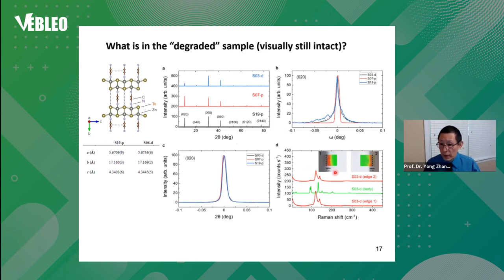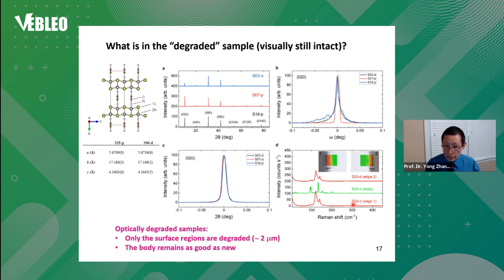To find out what is going on in the heavily degraded sample, we took a piece, cleaved it, and exposed the body of the sample. Then we did a Raman measurement from the edge. We found that in the body part — the green region — the spectrum looks just the same as the pristine samples. Only near the surface, around 2 micrometers, in the red region, they are degraded on both top and lower surface. So we know that only the surface is degraded, but the body is still as good as new, even after 15 to 16 years.